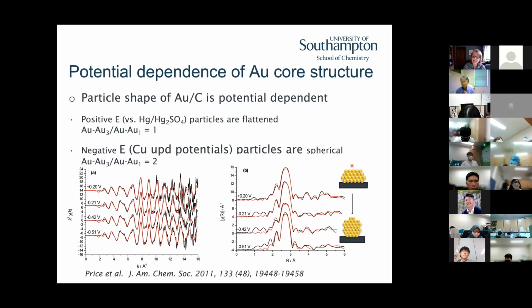And what this is telling us is that the shape of the gold particles is changing as a function of the potential. And that's really interesting because mostly in electrocatalysis, we treat those metal nanoparticles on a support as static blobs, right? We think of them as having a defined shape and they're just sitting there and they don't change. And I'm going to argue that many of the degradation processes that we see as we cycle these catalysts through oxidation and reduction, in terms of aging, is also because the shape is changing. The amount that the particle wets the carbon surface changes as a function of the potential. And so what we see is they go from being quite flat at the positive potentials, and as we go negative, they become much more round or spherical.